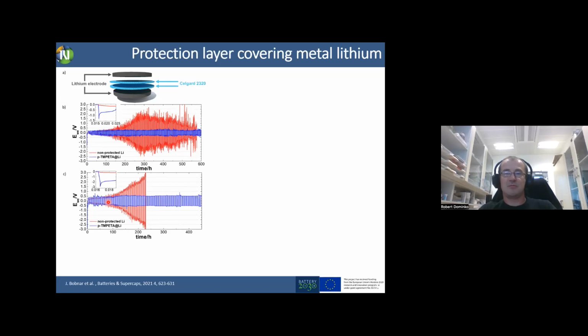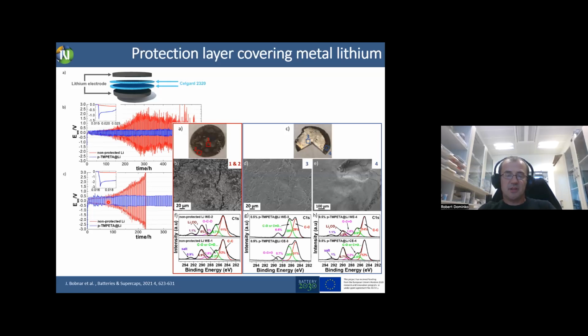Okay, great results, good proposal. But we wanted to know more. So we opened the cell, and of course, opening the cell where lithium was not protected, it is expected that you see this black coverage of the lithium metal, where high surface area lithium is formed, and going to higher current densities that can also create dendritic growth. On the other hand, the electrode that was covered with TMPTA remained metallic shiny, and okay, this is a good sign, so maybe that's really a protective layer, but the edges were highly damaged and also disappeared, as you can see here.